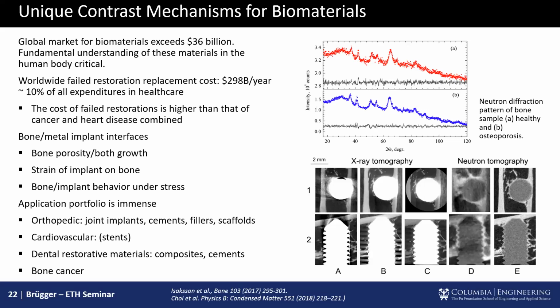But beyond that, there's actually now a push also in the 3D printing world to create and to design porosity at the interface between the human tissue or the human bone and the implant. And the goal here is to make that as gradual a transition as possible by actually increasing the porosity and increasing the surface area of the implant on the implant surface where it needs to fuse with the bone. So the higher surface area not only provides a cleaner interface and fewer stress concentration points, but it also actually increases bone growth because bone grows essentially as a function of the surface that it encounters. So the more surface area you have, the more it's actually willing to graft itself onto a foreign object.